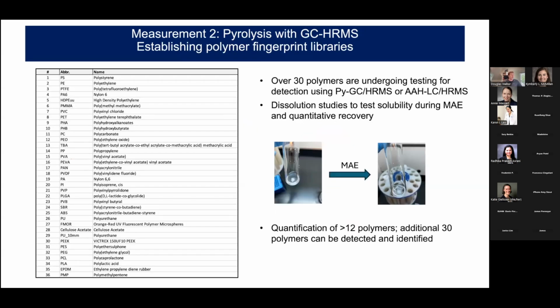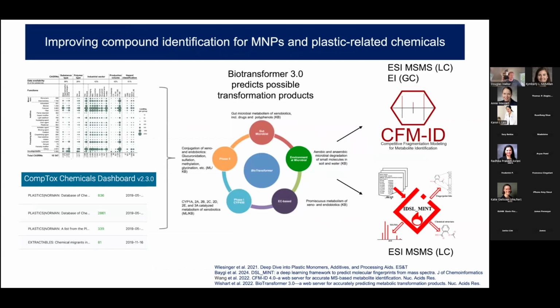We're doing a lot of other work trying to see what we can measure in these samples, but I did want to highlight that we're developing libraries of over 30 polymers that we can screen for in our samples. So we know what the signatures of these polymers should look like, and we can pull that data out with a high degree of confidence if we measure them. At the same time, we're also integrating quantitative workflows that allow us to measure up to 12 polymers and provide absolute concentrations of those polymers in tissues.